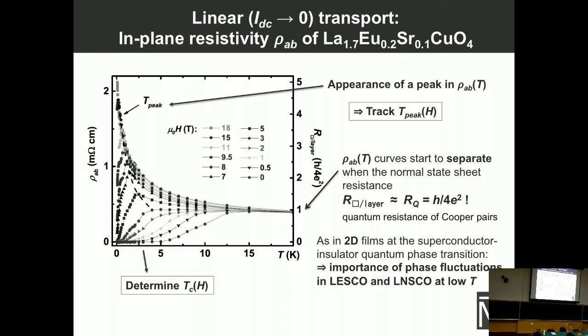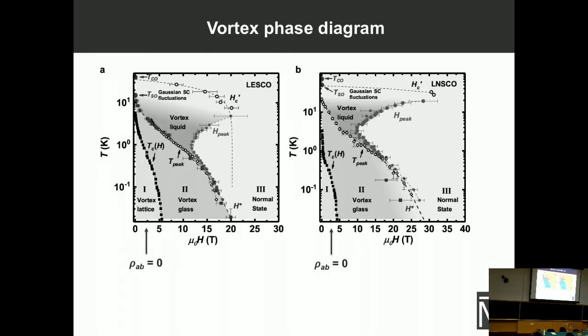Now it is striking because these are bulk materials. We have, I don't know, a million layers, and this looks much better than it does in 2D films. So this suggests that at lower temperatures, the phase fluctuations might be playing an important role, and we see the same thing in both materials. Anyway, we have these two characteristic energy scales. We have the peak in the magnetoresistance, and we can start mapping out the phase diagram.